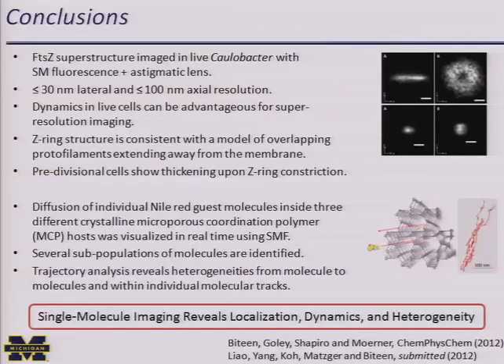What I was most excited about here, and what we're continuing to use in my lab a lot, is dynamics in live cells as our mechanism for active control. And finally, we were able to actually elucidate some biology, and so we saw the Z-ring structure did extend. It was overlapping filaments that extended away from the membrane, and that there was some thickening upon Z-ring constriction.